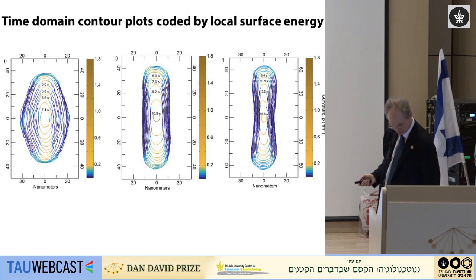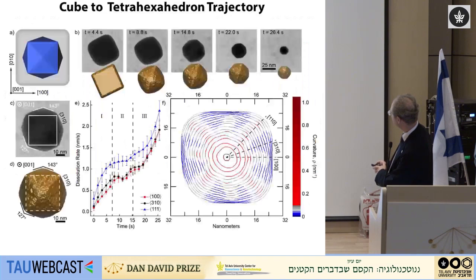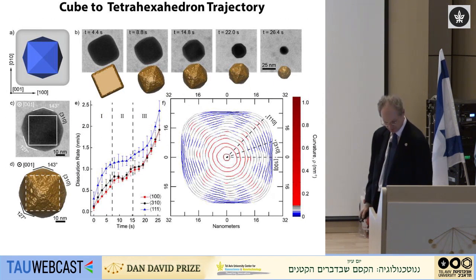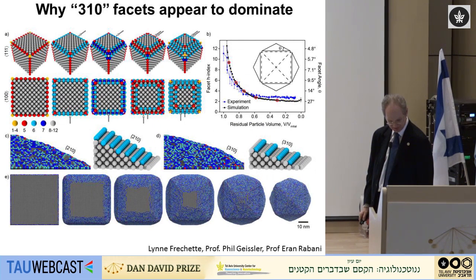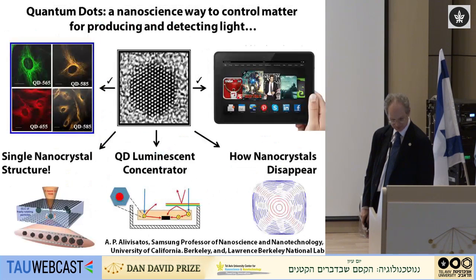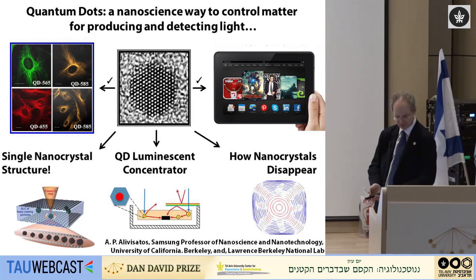Done. Okay. So I'm not going to go through all the details then, because I'm told that I'm done. But what I'll say is that we can make these diagrams that look, for example, like this, where you see these time domain contour plots. And if you go in and you look at them in some detail, it turns out that we can actually explain in some molecular detail why all the shapes that people have seen in the literature are showing up in a very quantitative way that differentiates between slow and fast growth and other features like that. So the liquid cell is now moving into a stage, I think, where it's becoming extremely quantitative, and it's going to become a very powerful tool.